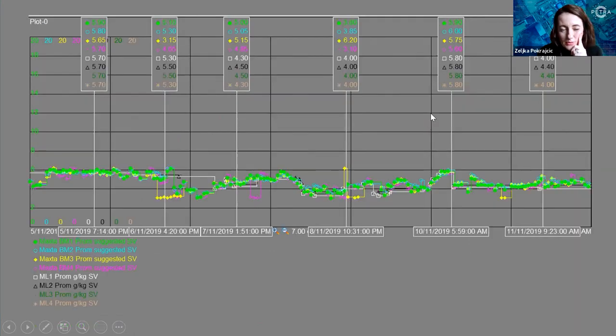Okay, so this is where it gets fun for us metallurgists. If we're predicting what the quality of the material is coming out of that flotation plant, which is called the rougher scavenger tail, we can suggest, using conventional mathematical techniques, what the operating parameters should be. So here we have prom, which is promoter. These are reagents going into the plant, and we're suggesting what reagents and what levels in the cell it would be to maintain optimum performance based on historical data.